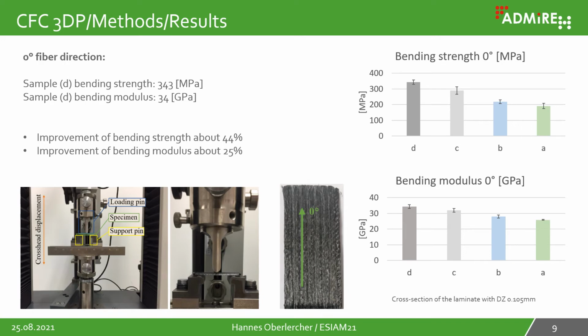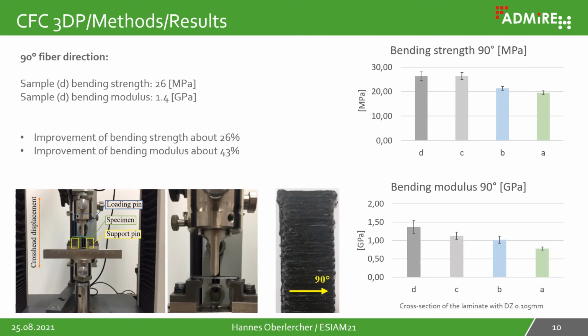It was a big improvement from sample A to D. You see that the bending strength could increase about 44%, and also the bending modulus about 25%. In the 90 degree fiber direction, sample D also showed the best bending properties: the strength was about 26 megapascal and the modulus about 1.4 gigapascal.